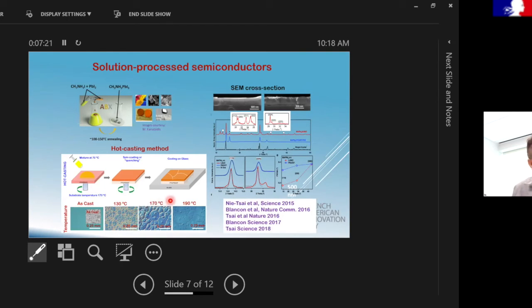And so you could see that we could actually make these very large grain sizes. You can see them with an optical microscope, and we could get them as large as 1 millimeter. And then if you actually look at the diffraction, you'll see that you get these sharp peaks. And this is typically not what you see for solution-based materials. Typically, you see this broadening, which is representative of defects or disorder in material. And so this is the first time that you could take a solution-based material, spin coat it, and get these peaks, which you would get in semiconductors, which are processed using high temperature. So that's the first thing that was quite amazing about these materials.